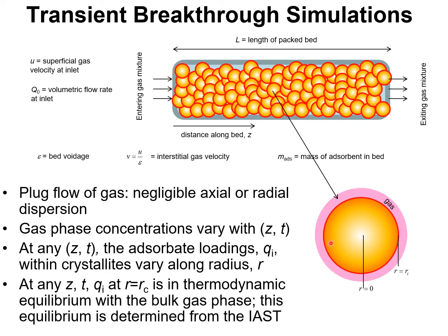Each crystallite of MOF or zeolite is surrounded by a gaseous mixture, and at the surface of the crystallite the gas mixture is in thermodynamic equilibrium with the adsorbent. The mixture adsorption equilibrium is determined in the simulations using the ideal adsorbed solution theory.